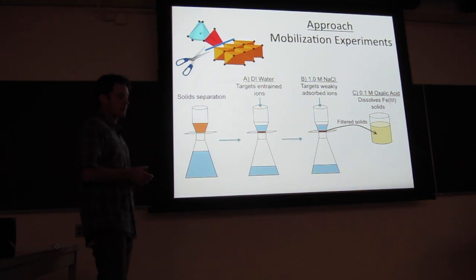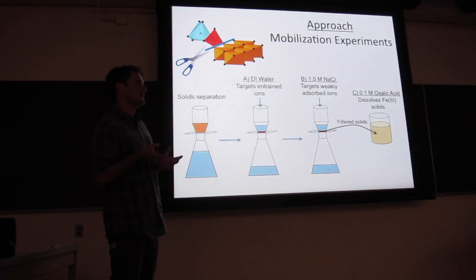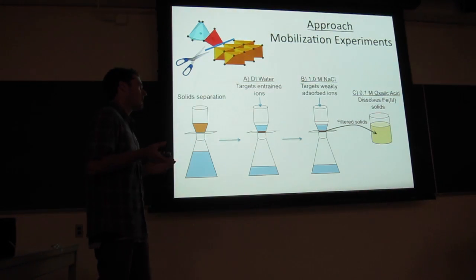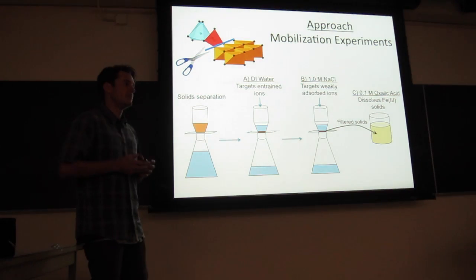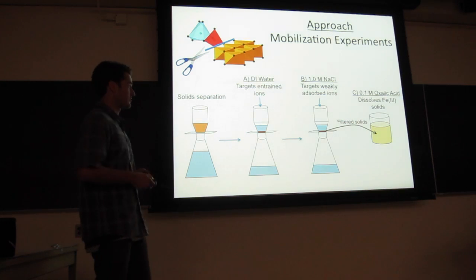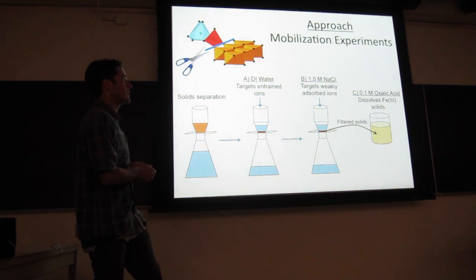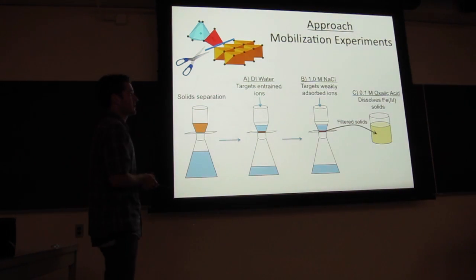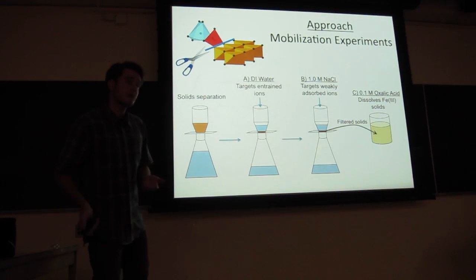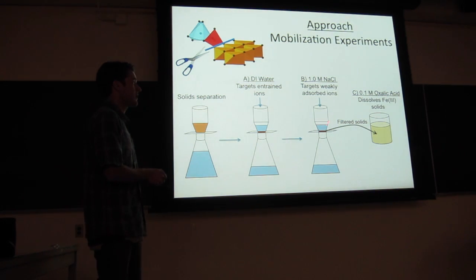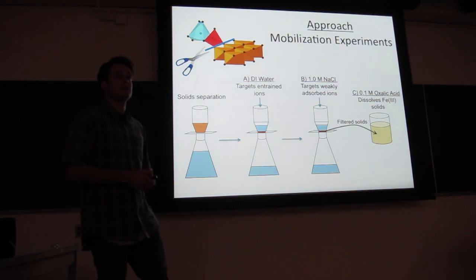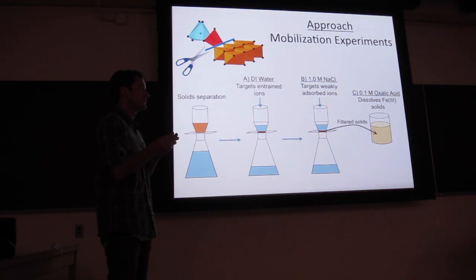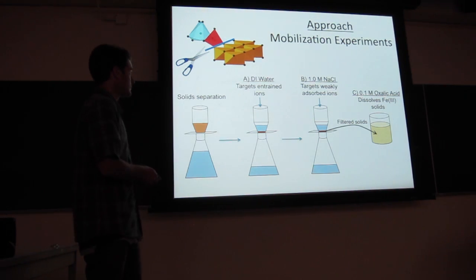So the DI water targets entrained ions, and what I mean by that is ions that are not really associated with the oxide, but more stuck in the pore spaces, for example. So this is kind of like rinsing it. Then we pass 1 molar sodium chloride, and that's designed to target weakly sorbed ions, something like an outer sphere complex, for example. And then we take the entire filtered solids and digest them in oxalic acid, and that dissolves the iron oxide. And so this is going to be targeting all of the really strongly sorbed ions.